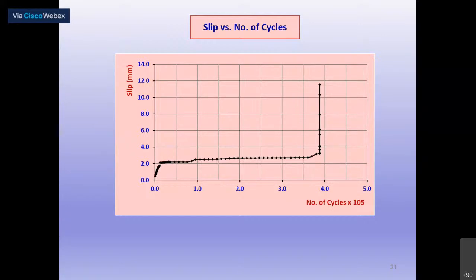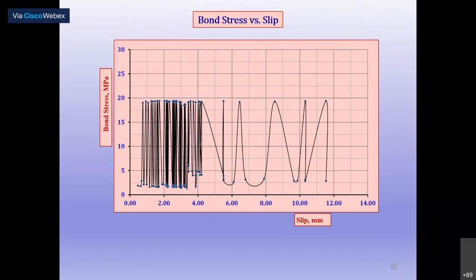So we found that up to 3.78 lakh, it was working fine. Due to overloading, the failure occurred in the early stages. This is what cyclic loading is: minimum stress at the bottom level, maximum stress level at the top. So we have to apply this way, the bridge will be subjected to minimum and maximum stresses, and we define the life of the bridge.